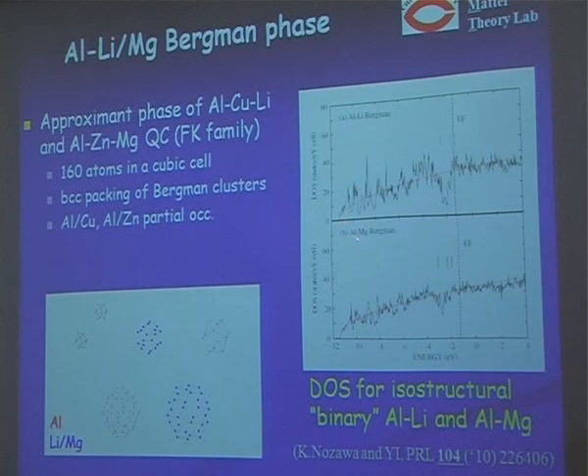But in the aluminum-magnesium case, we have only a shallow pseudo gap here, and the density of state looks more like that of nearly free electrons. So both of these systems have the same structure. But we have a very deep pseudo gap in one case, and a very shallow pseudo gap, or nearly free electron-like density of state, in the other case. So it is very different.